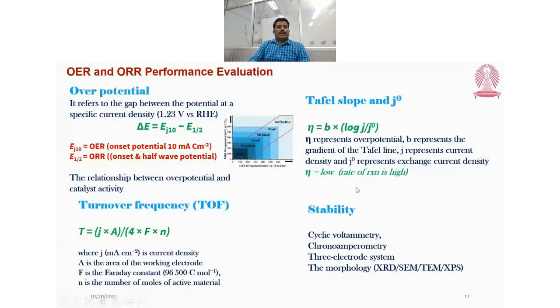How do we evaluate the OER and ORR reactions? Here I am showing four methods. First, overpotential. Overpotential is the most effective method to evaluate the reactions. It refers to the gap between the potential and the specific current. If you have a bifunctional catalyst, we can use this equation: delta E equals Ej minus E1/2. Here Ej is the onset potential of OER and E1/2 is the half-wave potential of ORR. This gives the graphical explanation. If we compare our catalyst in this graph, we can tell whether our catalysts are excellent or poor.